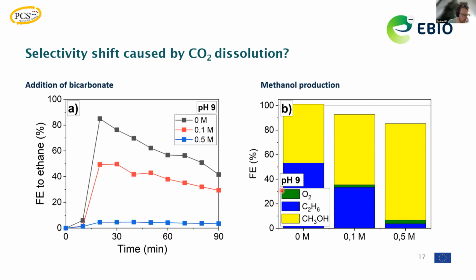So I can tell you, we tested quite some electrodes already to do Kolbe oxidation, and none of them were yet being active actually. So far it has been platinum, and of course, you know that we're also working with BDD, but then we have a stability issue quite fast. So we are now more considering using support structures and functionalizing these supports with platinum, so that we do not need to make use of thick platinum layers, or thin films as we have been using here. So to basically just reduce the platinum loading in these cases. But because of the oxidative potentials, the interaction between the support and platinum needs to be very good. Otherwise, you might have under-etching, and then you lose your platinum in the end. And that's something that still needs to be figured out and is on the to-do list.